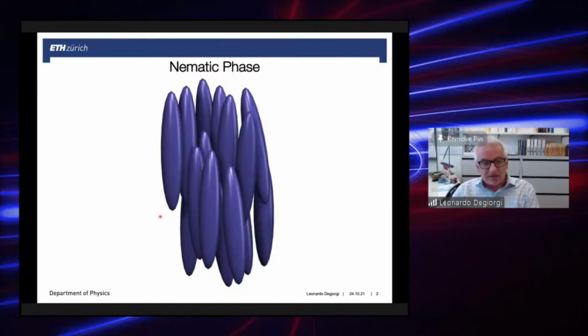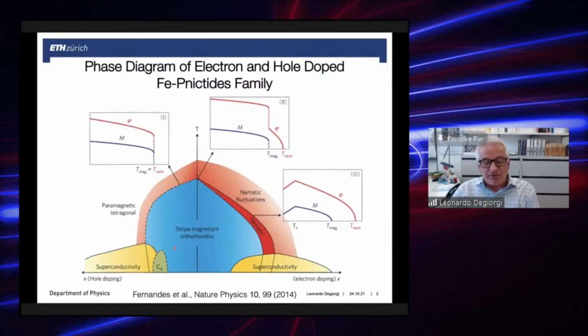In this context, I would like to show you the phase diagram for the iron pnictide family, either the hole or the electron doped. But a similar phase diagram can actually be obtained also for other types of iron-based superconductors. The point here is that there is, particularly in the underdoped regime, a tetragonal to orthorhombic phase transition, which indeed breaks the fourfold rotational symmetry of the tetragonal phase, and this was indeed ascribed to nematicity.